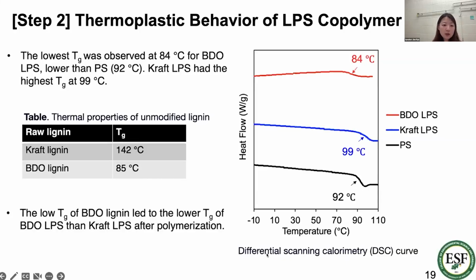As we can see in the table on this slide, the glass transition temperature of Kraft lignin was 142 degrees Celsius, and BDO lignin showed a lower glass transition temperature than the Kraft lignin, at 85 degrees Celsius. This result indicates that even after we modify the lignin structure, the raw material's thermal properties are still very important for the final thermal properties of the LPS copolymer.